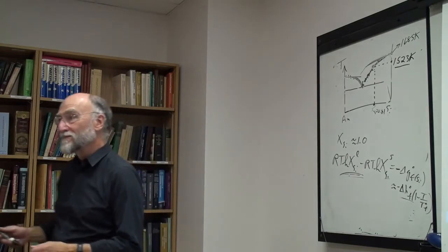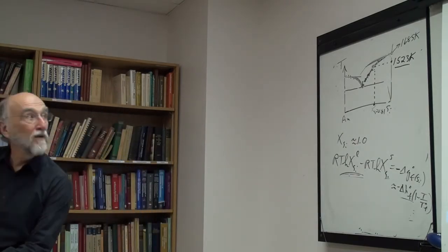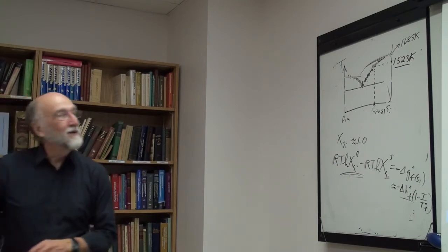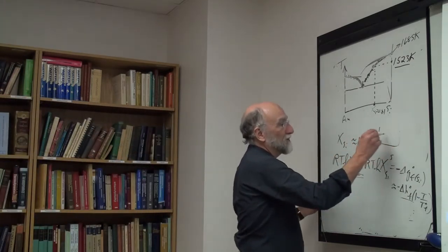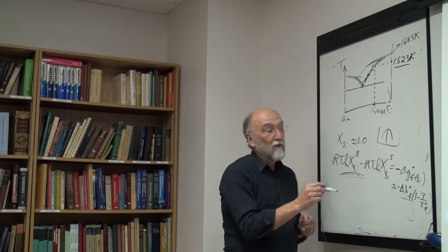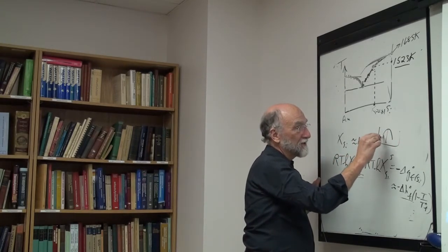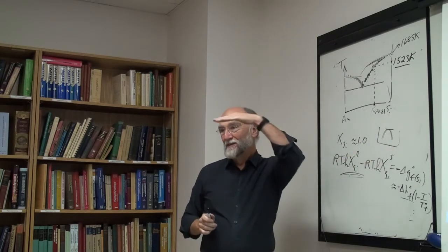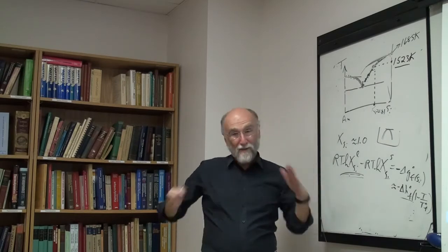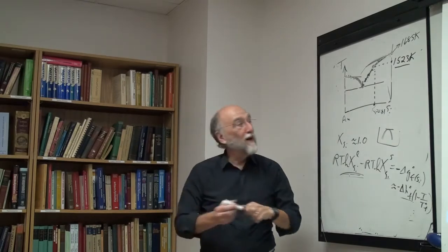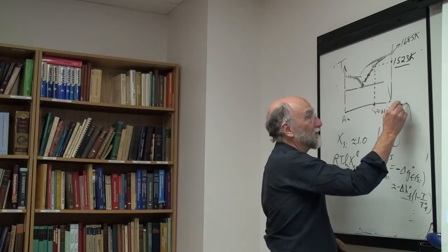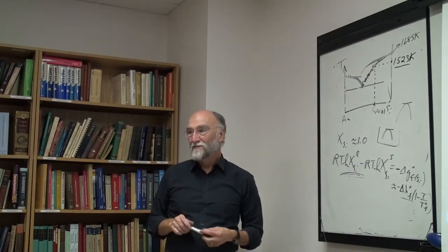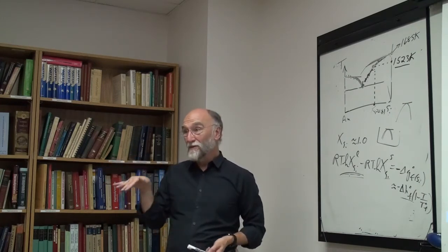Is it also applied to a metal compound? Yeah, but to what? To an intermetallic? No. Because in an intermetallic compound, remember, this is really a maximum in a two-phase region, right? And the limiting slope is 0. It doesn't come up like this, it comes around like that. It might look very much like it comes up strong, but it really doesn't. The limiting slope is always 0, theoretically.